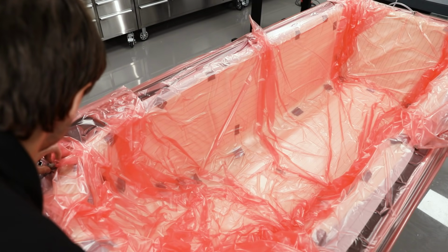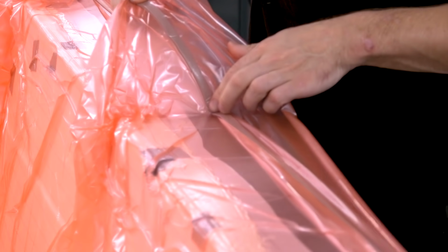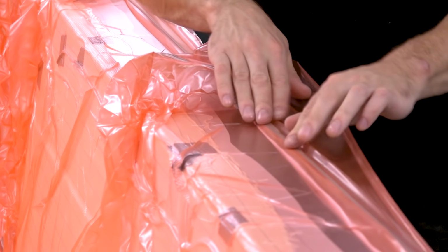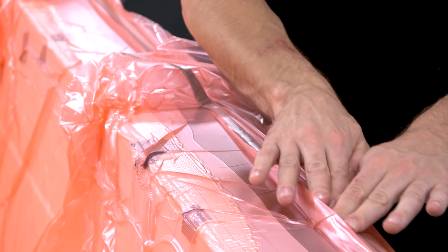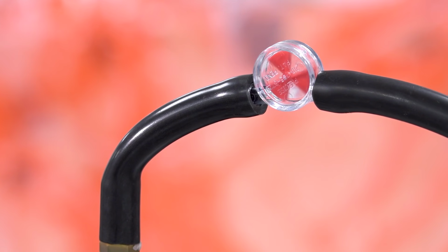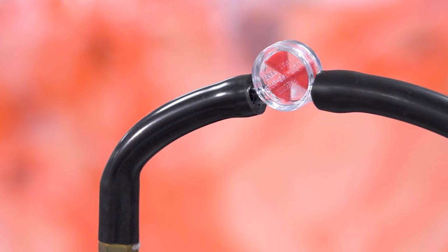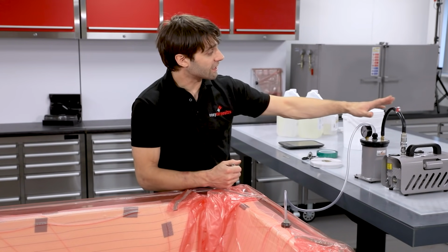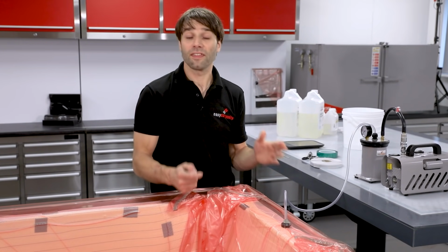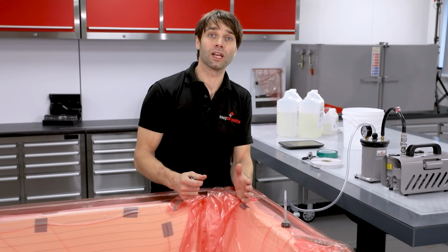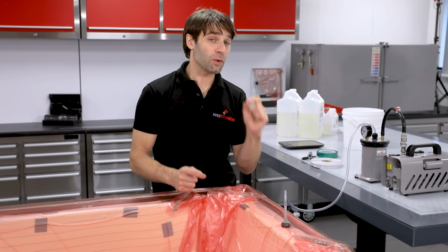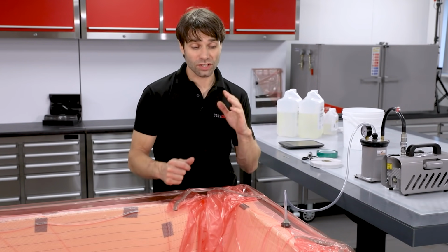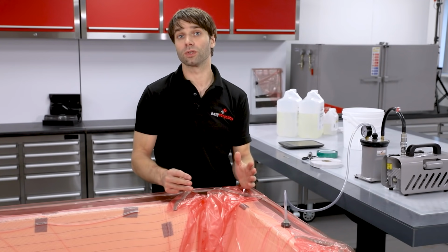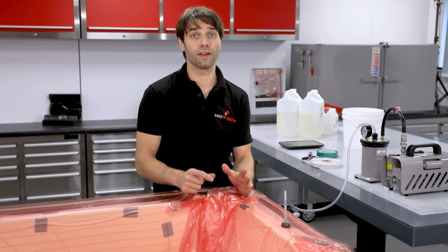While the vacuum is pulling down, it's a good opportunity to take a lap around the seal, inspecting it and pressing it down further. If you're using a leak flow indicator, you're waiting to see this stop moving to show that the bag has been fully pulled down. I've got the vacuum pulled on this bag, and as you can see, the leak flow indicator stopped spinning. That indicates that we've got a well-sealed bag. What it doesn't indicate though is if we've got a perfectly sealed bag. And there's absolutely no point in running a resin infusion unless you know that your bag is perfectly sealed.